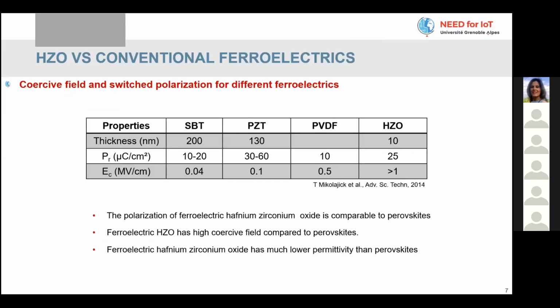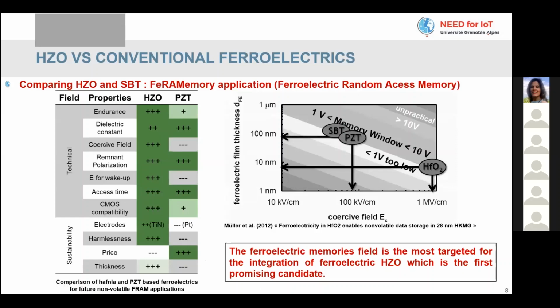Comparing to other conventional ferroelectrics, the hafnium zirconium oxide has very interesting properties, such as very small thicknesses compared to ferroelectric ceramics and PZT or even ferroelectric polymers. As a comparison for one application, ferroelectric memories, here we compare the hafnium zirconium oxide with PZT. It gives very interesting technical properties compared to PZT, and even in terms of sustainability, the use of titanium nitride electrodes compared to platinum is very sustainable. And PZT contains lead, which is prohibited in industry since 2013.